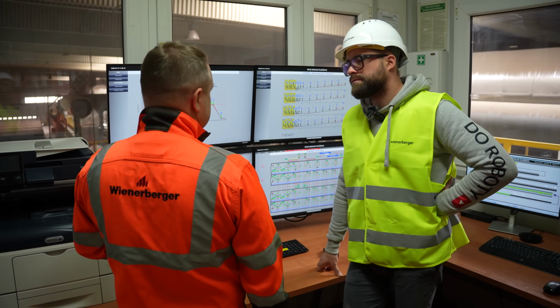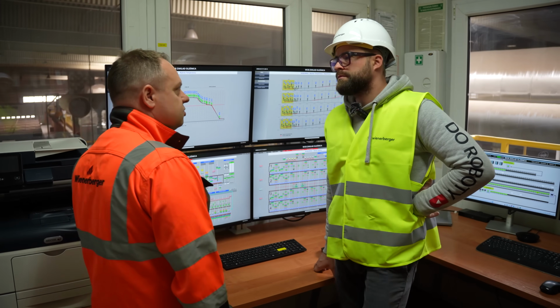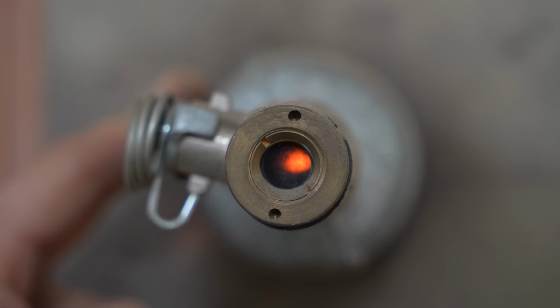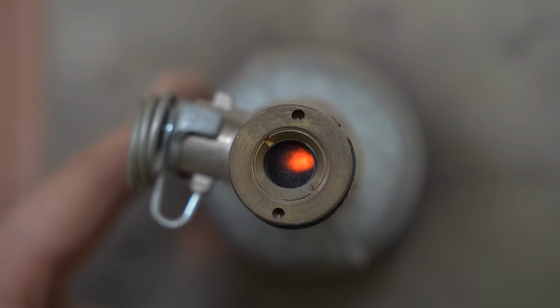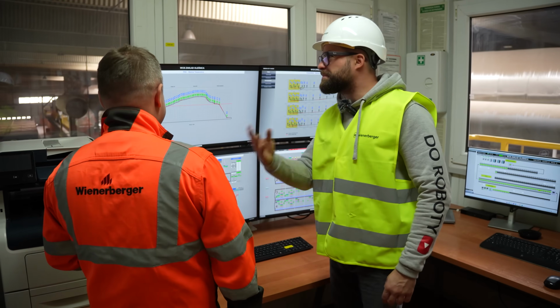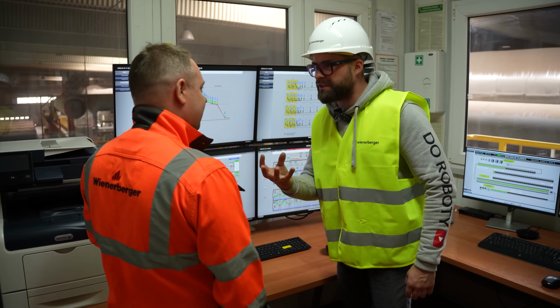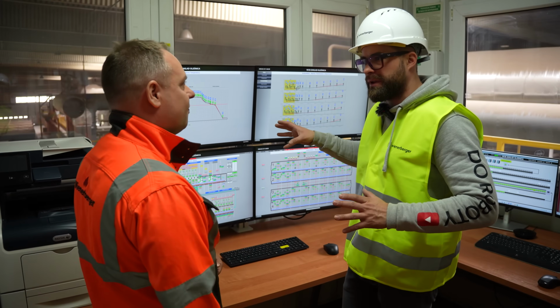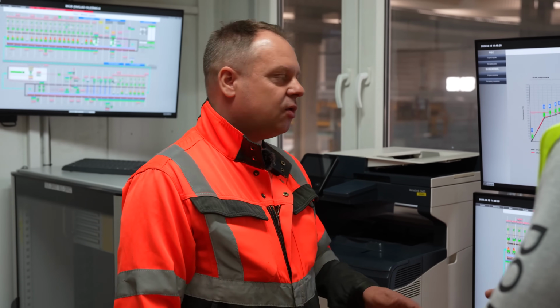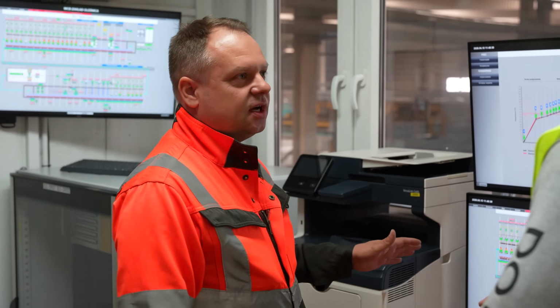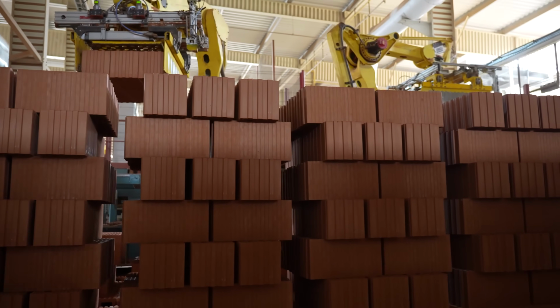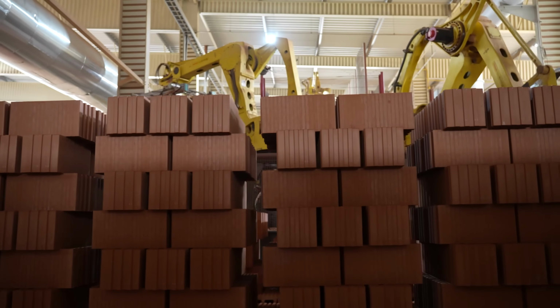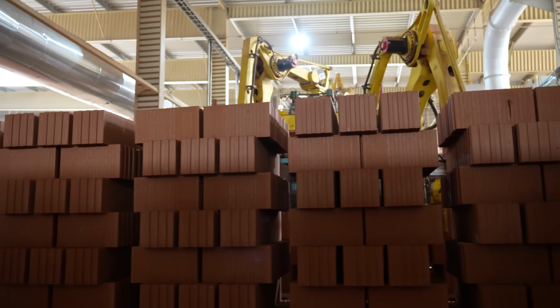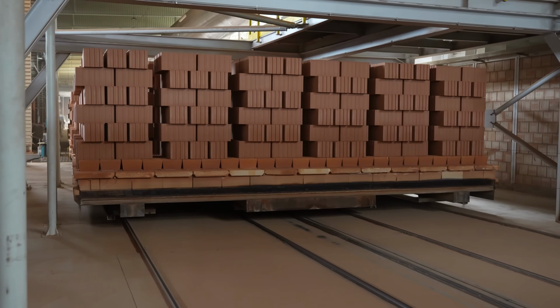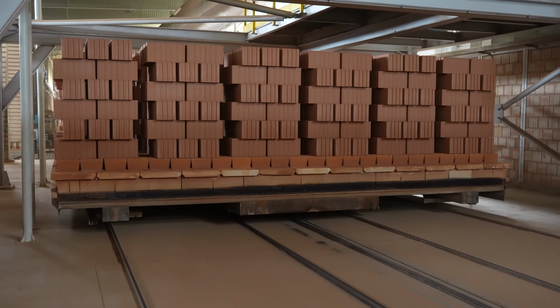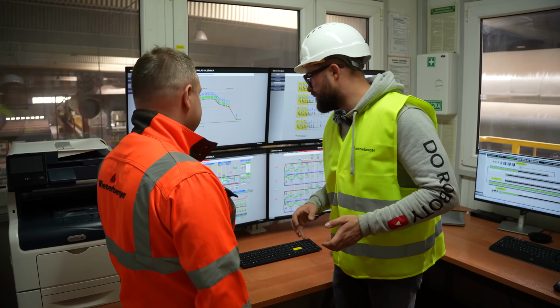The firing temperature is about 900 degrees. As you've probably already noticed, we have a viewing port where you saw that the brick simply glows there. It's hot. So first we dry the brick for 12 hours, and then we fire it for another 18 to 19 hours. Then, after the firing, it comes out of the kiln and moves on to the next stage. You'll go to the unloading area where there's also a cooling channel. We recover the heat from those carts and then transport it to the dryer to increase our thermal efficiency.